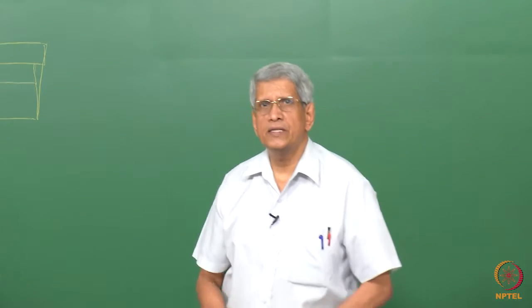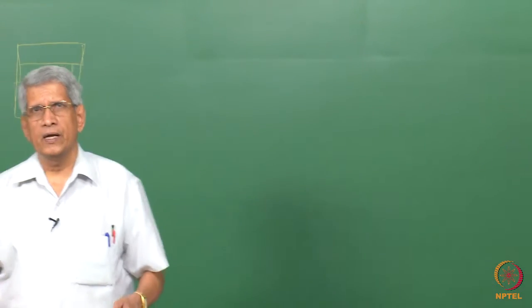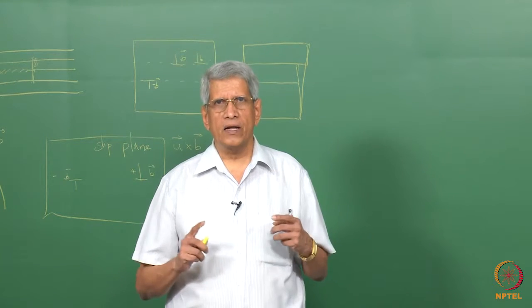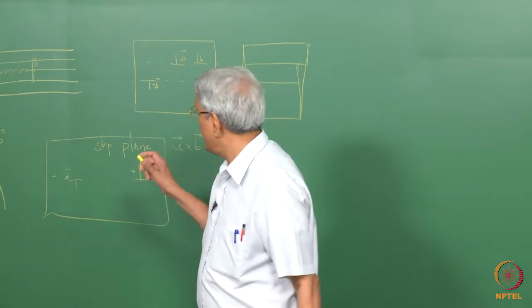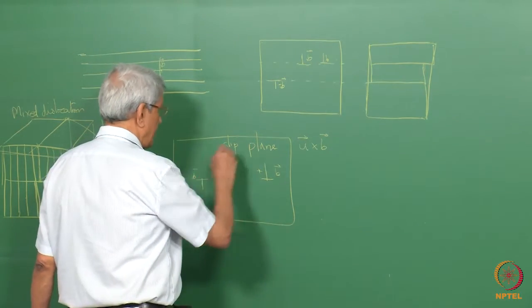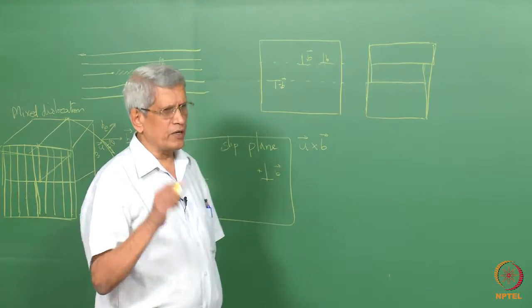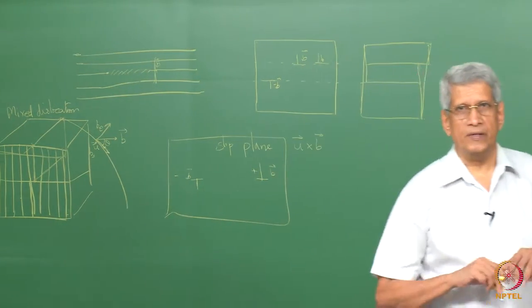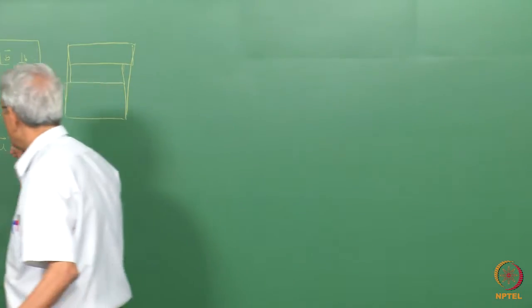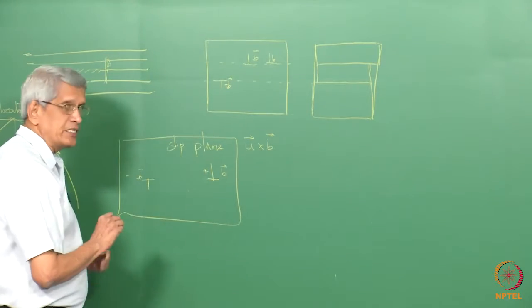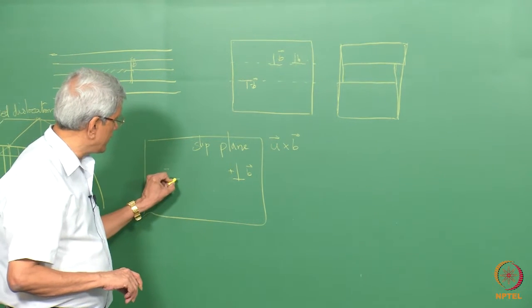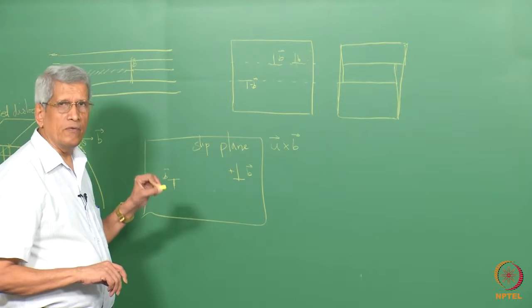So, if a dislocation cannot end within a material, the two options it has are that it can come out of the sample surface or it can form a loop, so that we cannot define where it starts and where it ends. By forming a loop, we can make a dislocation which satisfies the condition that it neither begins nor ends within the material.